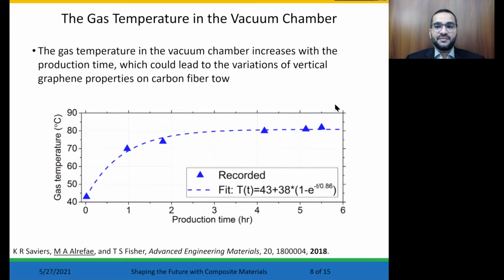The observed changes of the properties of graphene-coated carbon fiber along the tow are related to the increase of the gas temperature in the vacuum chamber, as shown here. This temperature is for the gas temperature outside the plasma region, and it indicates a warm-up period in the first half of the production time. So, light to medium coverage of vertical graphene deposition on carbon fiber occurs in the first half of the tow, as discussed in the previous slides. When the temperature stabilizes in the second half of the production run, uniform and abundant deposition of vertical graphene occurs.